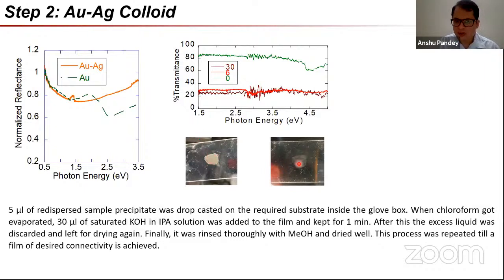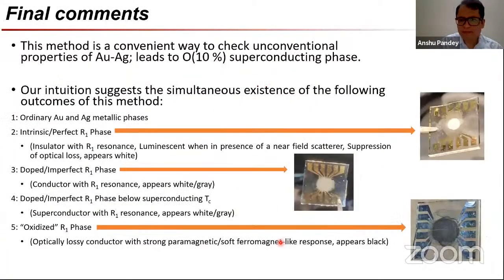Any attempt to expose, so this film casting has to be done in a glove box which is around 1 ppm or so. We have worked in situations where it has gone up to 5 or 10, but then the results get rapidly unreliable at that point. These films which we cast, if you have any amount of air exposure, they darken almost immediately. So from white they go to a totally black film. This is accompanied by a sharp fall in the transmittance. So that's essentially what it looks like.